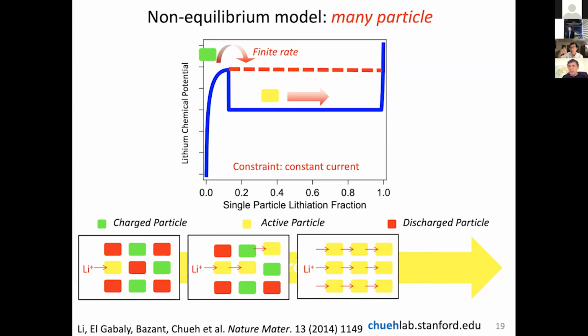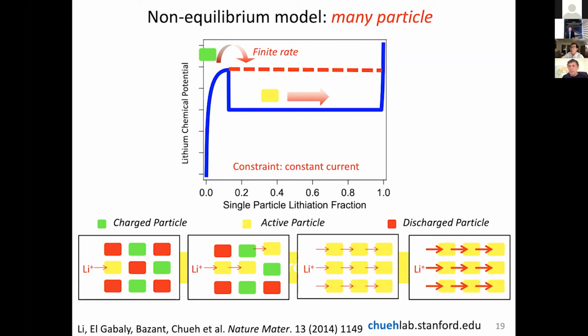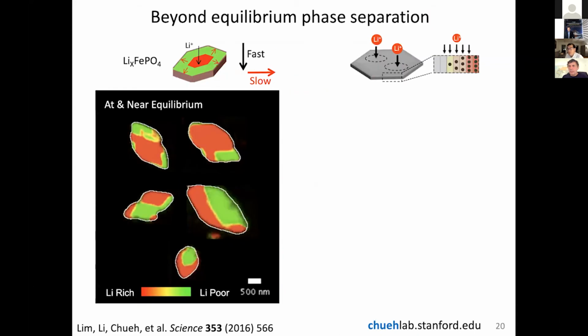What you're tuning here is the nucleation rate. And this is where the active population concept comes in. It's not until all the particles become active that you start raising the red line considerably higher, because now in order to deliver a higher current, you need to increase your driving force beyond the nucleation. Basically, this is when all of the particles have exhausted the nucleation event. So this is a brief insight into the active population effect in lithium iron phosphate.